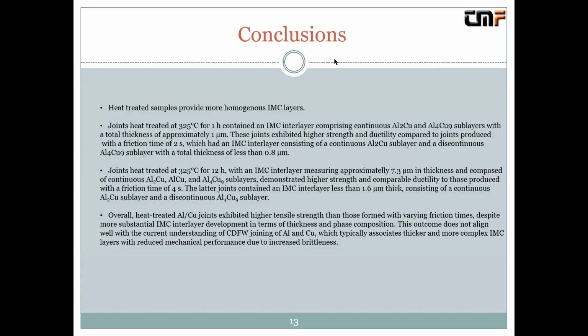So what's, I think, obvious from this presentation is that the main difference between samples which we made during the continuous drive friction welding and heat treated samples was the homogeneity of intermetallic layers. During heat treatment, we obtained more homogeneous intermetallic layers, in terms of composition and in terms of thickness.